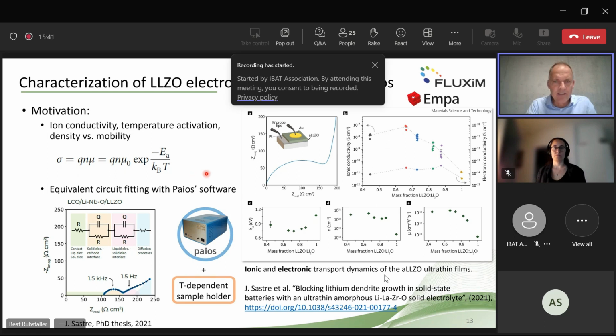So you measure these impedance data, for instance, shown at the bottom left, a semicircle and something that doesn't look like a circle, but then the equivalent circuit model allows you to fit that data, the black line here. And another example is this sandwich device where an electrolyte was put in between two electrodes. The impedance measurement is shown here.